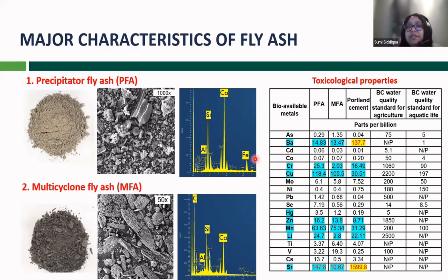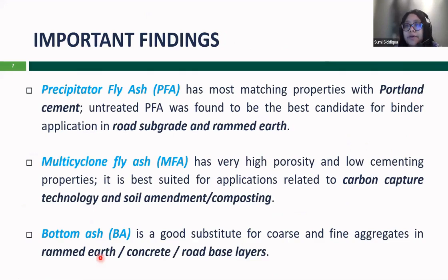So these information give us a very strong feeling about the material, and we were excited to take this material into the next stage. So a few important parameters we have identified from that. We have looked into the 3 different types of fly ash from the pulp and paper mill. First one is the precipitator fly ash, and has the most matching properties like the Portland cement. Untreated PFA was found to be the best candidate for binder application in road subgrade and rammed earth. So that PFA was the candidate material for us.